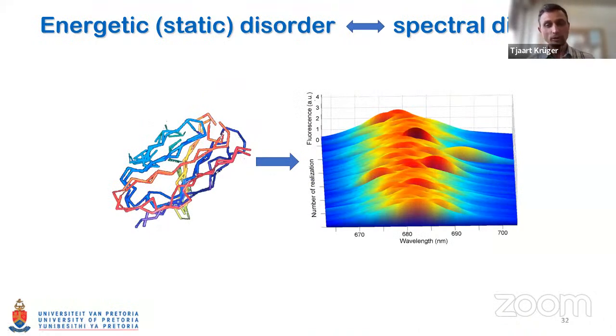Okay, so we wanted to find out what is the origin of this significantly redshifted emission. And we firstly did some modeling, to investigate the role of static disorder. So static disorder is related to the natural fluctuations of the protein backbone. And because the pigment molecules are strongly coupled to the protein, any fluctuations in the protein will be translated to fluctuations between the pigment positions, and that will lead to changes in the coupling and the orientations between these pigments. So that will give rise to spectroscopic changes. That is predicted. So here's a spectral series that is predicted by static disorder giving rise to spectral diffusion.